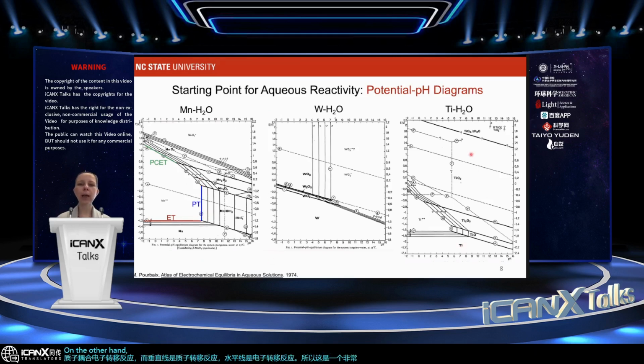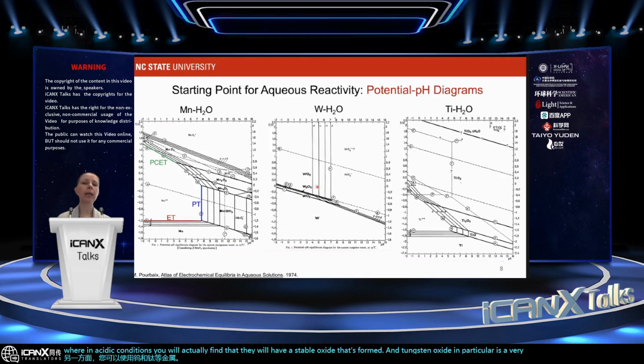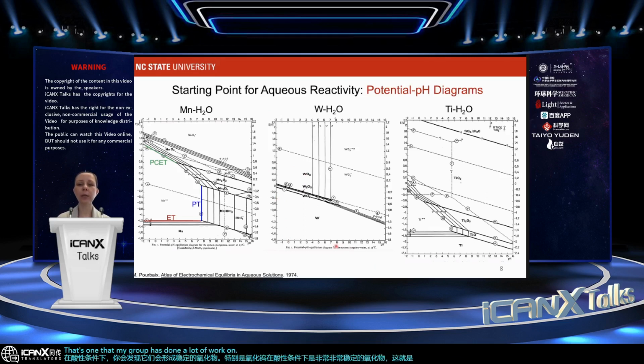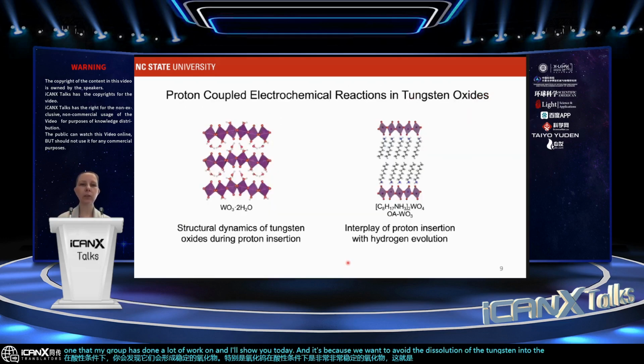On the other hand, you can have metals like tungsten and titanium, where in acidic conditions, you will actually find that they will have a stable oxide that's formed. And tungsten oxide in particular is a very, very stable oxide in acidic conditions. And that's one that my group has done a lot of work on, and I'll show you today. It's because we want to avoid the dissolution of the tungsten into the electrolyte. We want to maintain the solid state structure.